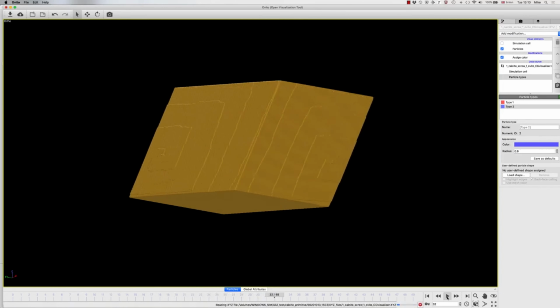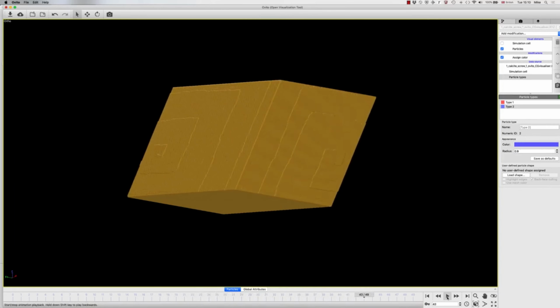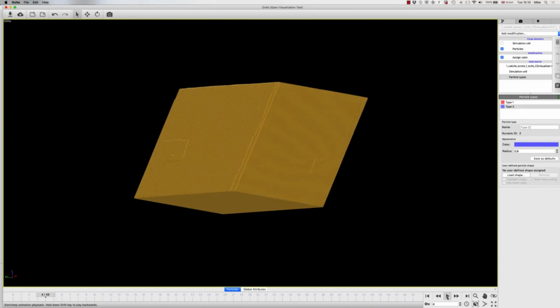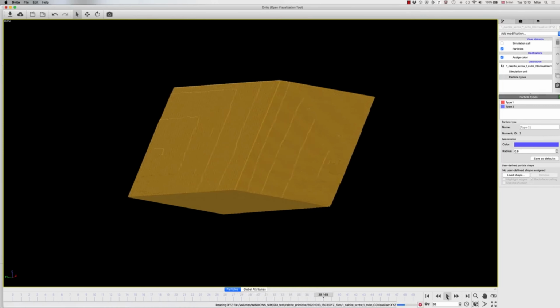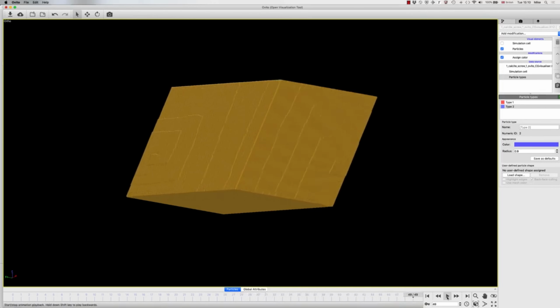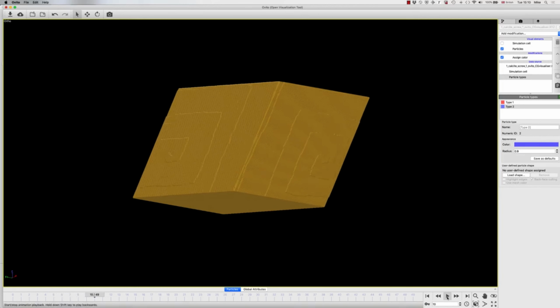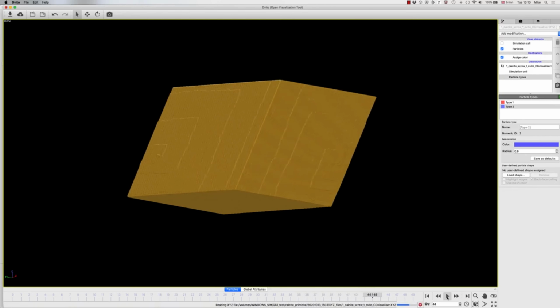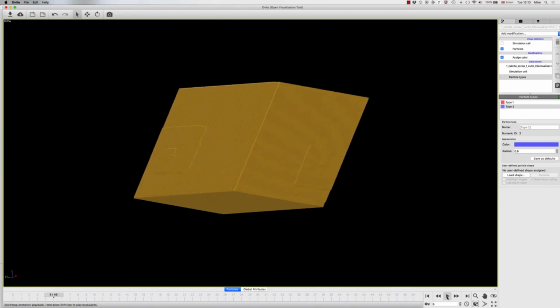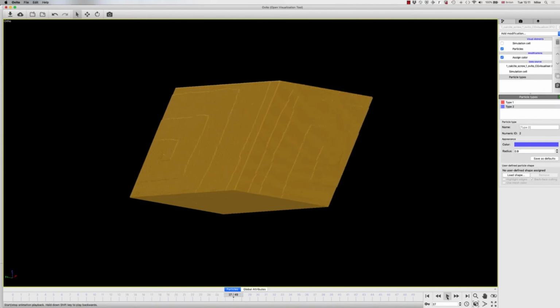So what you want to be careful is not to use the information just from the first few frames, or what I would normally do is actually start recording slightly later on in the movie after the structure has healed itself. But the nice thing about doing it this way is that you can grow yourself a large seed crystal with a fast, rapid simulation, because it would take quite a long time to grow that with the screw in place, and then you can do your growth on top.